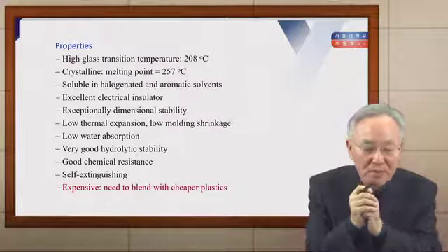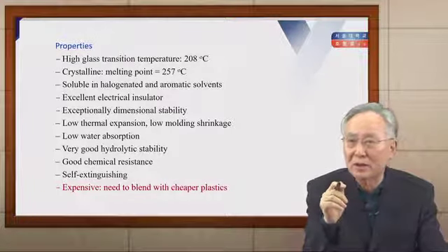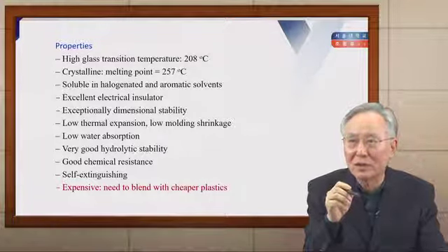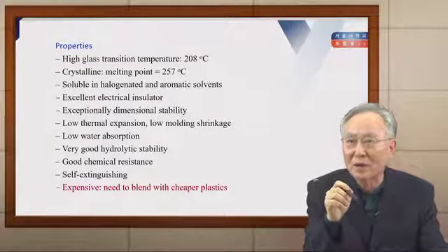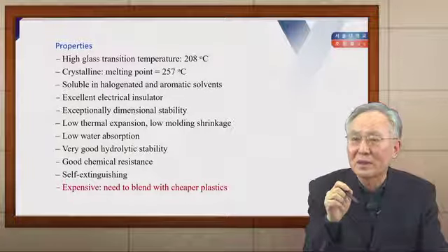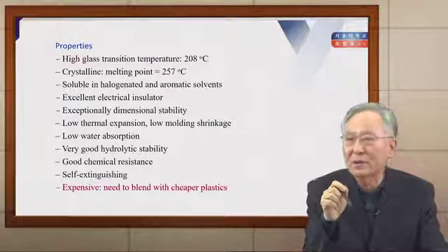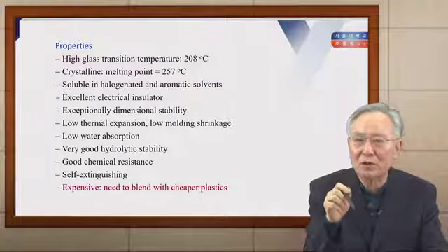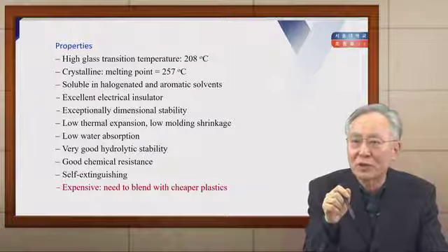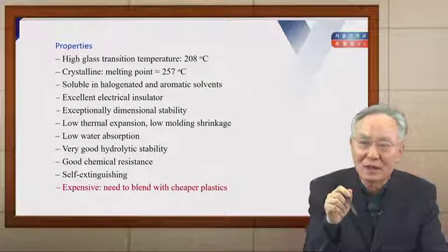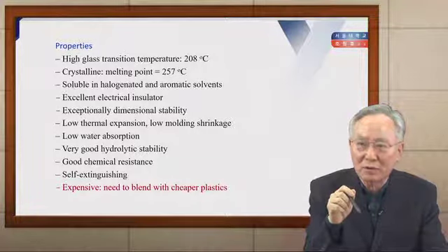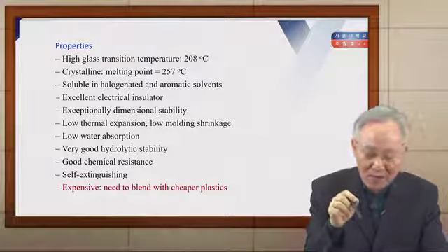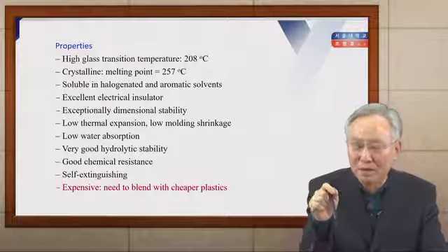PPO has many good properties. Its Tg is very high at 208°C, and it is crystalline with a melting point of 257°C. PPO is soluble in halogenated and aromatic solvents, shows excellent electrical insulating properties, exceptional dimensional stability, low thermal expansion, low mold shrinkage, low water absorption, good hydrolytic stability, good chemical resistance, and self-extinguishing behavior. However, the critical disadvantage of PPO is that it is very expensive, requiring blending with cheaper plastics.